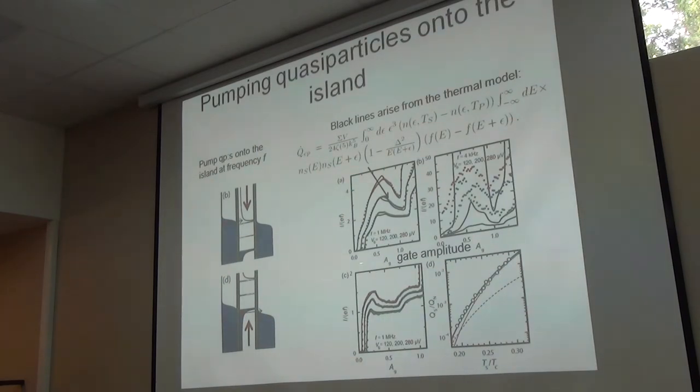So this is the amplitude of the gate, and here is the current through it. You can see that the experimental data look pretty non-trivial there. The shape of the curve is something you would not intuitively be able to tell immediately what it comes from, because there are many different features in this device. But nevertheless, this straightforward model fits the data almost in all its details, with just a single prefactor as a parameter, and even this prefactor is known quite well, because these are material parameters that we know. So that was very pleasing, that we can explain the transport characteristics quite nicely with this model.